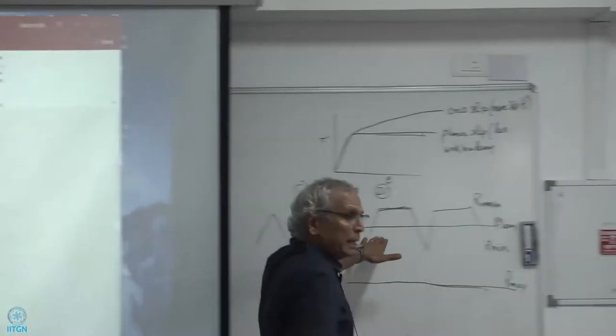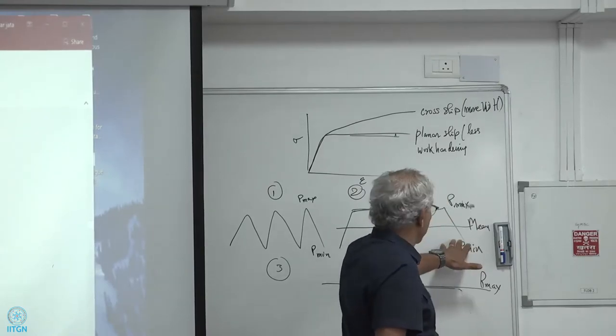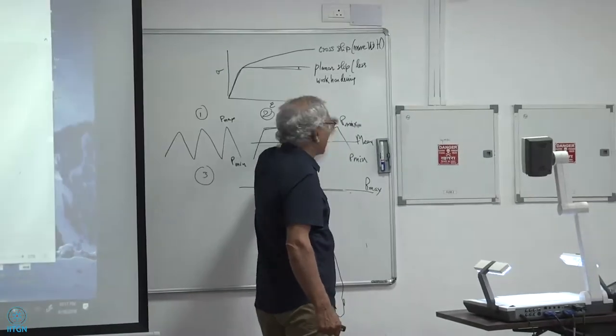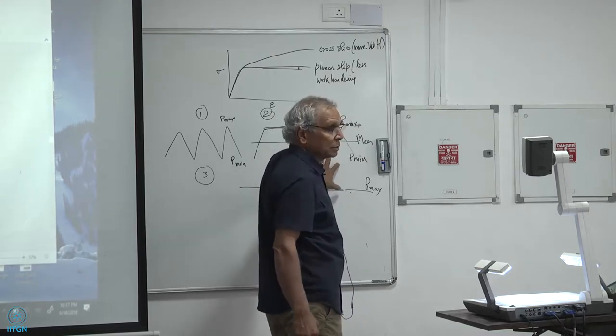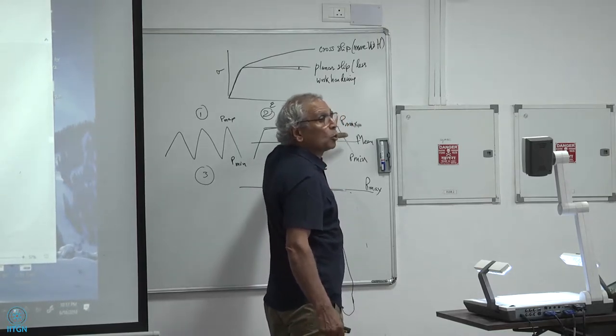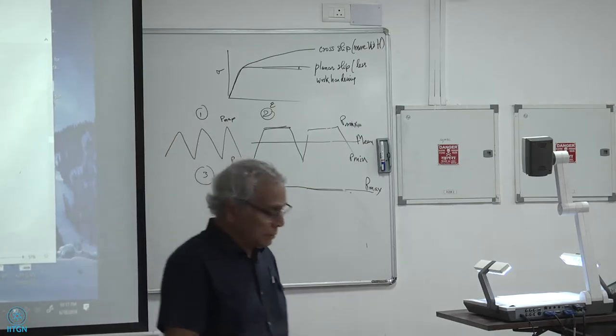That's the creep strain you're getting in the most bottom one, which is the titanium 6-4. So it's not a whole lot, but it is there, 0.04% creep strain. And if you have a good extensometer, a capacitance gauge, that's what they use most of the time to get those kind of strains. They can put the capacitance gauge outside the furnace. You don't have to put it inside the furnace. You can put it outside the furnace, and it's very accurate, very, very sensitive.